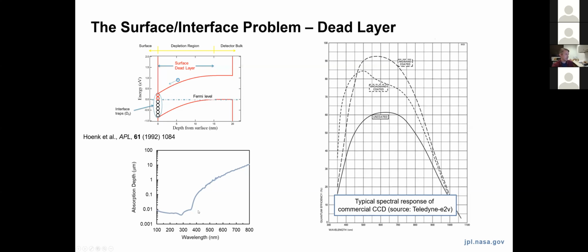And so that means for those ultraviolet photons that get absorbed in just the first few nanometers of the silicon, instead of moving down into the detector part of the sensor, they fall back and get trapped in this well. And so that's the dead layer problem.